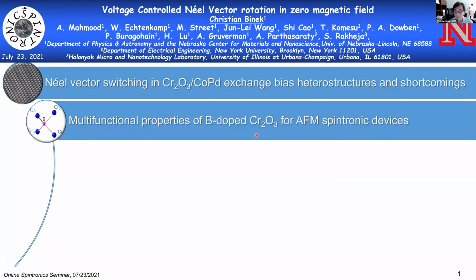It has a Néel temperature of 307 Kelvin in the bulk, but that's not sufficient for those applications, as you know. And it was in fact DFT work done by Kirill, who proposed to do boron doping to increase the Néel temperature. And we did that, and we did increase, as predicted, the Néel temperature. But with that, to our own surprise, came multiple other changes in the system, some good, some not so good.